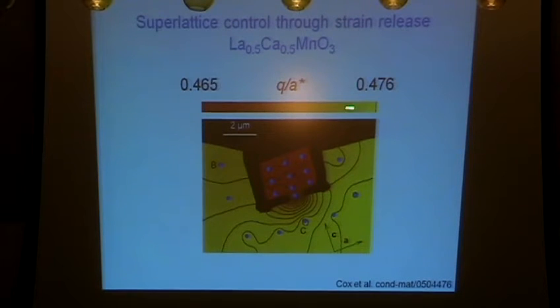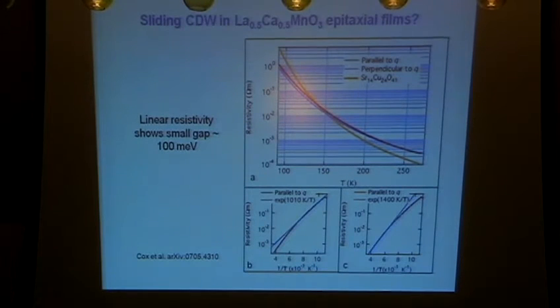So this is a sample which has been thinned and a piece cut out of it. So you're looking down on the top. These different colors, this is wave vector one, this is a different wave vector here. And so this is less strained from the substrate than this one, and you discover that the charge order decides to move to a different period. It's easy to move around.